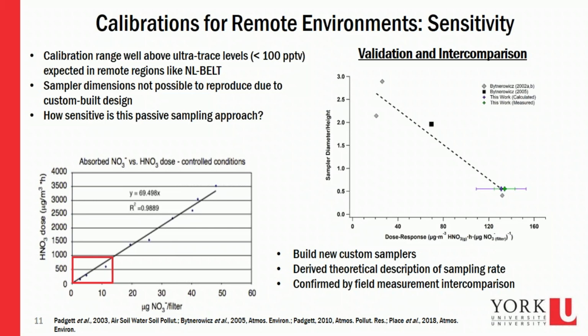And then we did an active intercomparison where we took our samplers to very low concentration areas, ran them side by side with the typical technique like an annular denuder, and found that we got the exact same sampling rate out of that. So it looks like we actually have a pretty good description there. So we have a validation of the sampling rate for very low concentration environments. We've confirmed that we're capable of making that measurement very sensitively.